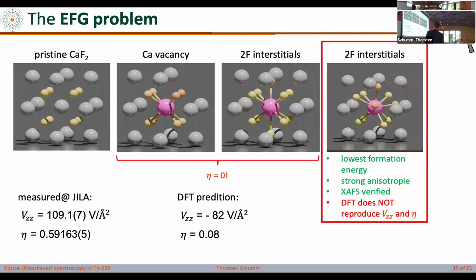So the theoretical prediction, in this case, is minus 82 volts per angstrom squared, and we experimentally find about 110. And the minus sign is a difference in topology. It's not just, oh, if I turn around my Cartesian coordinates, it will change sign. It's more involved than this. So it really means it's very different. From a topological point of view, this and this look dramatically different. It's not just numbers being slightly off or within error bars. So there's something that we fundamentally don't understand.